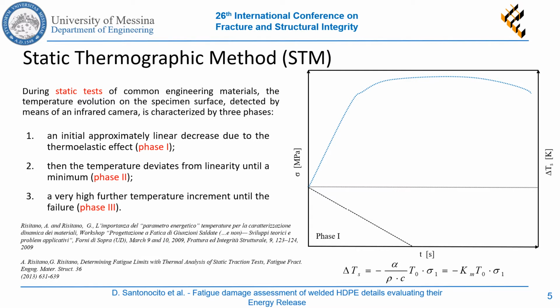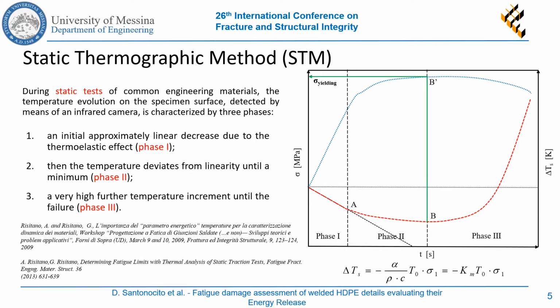An initial approximately linear decrease due to the thermoelastic effect following Lord Kelvin's law. Then, in the second phase, the temperature deviates from linearity until a minimum, and finally it experiences a very high further increment until the failure.